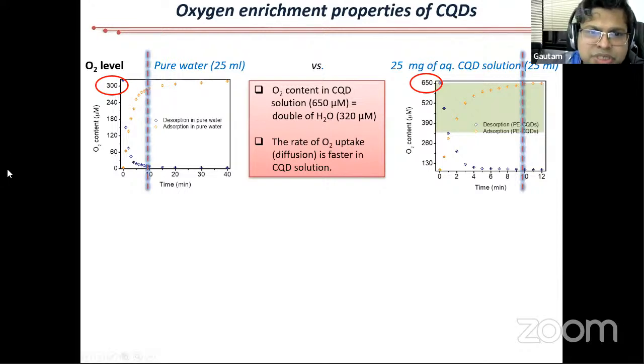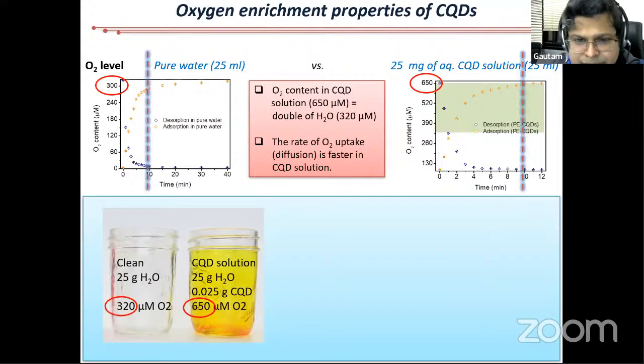So this process, in this experiment, takes about 10 minutes in water. And this takes only 4 minutes in CQD solution. So the oxygen diffusion has also become very fast. Oxygen amount as well as oxygen diffusion has become very fast.